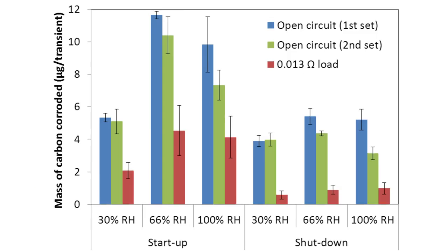So what use was this? What does knowing this let us do? Well, we were investigating a way of mitigating this type of carbon corrosion by applying a small load across the cell on startup and shutdown. And when you do that, you can significantly reduce the amount of carbon corrosion that you see. And as you'll see, particularly on shutdown, it's a very effective way of stopping this carbon corrosion from happening.